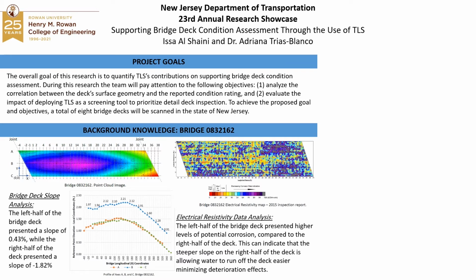By having a look at the results obtained from the 2 different assessment methods, we can tell from the bridge deck slope analysis, by looking at the gradient of the color for the left side of the bridge, that it has a flatter slope than the right side of the bridge. The results showed that the left side had a 0.43% slope, while the right half of the deck presented a slope of -1.82%. Taking a look at the electrical resistivity data analysis, it shows that the left side of the bridge presented higher levels of potential corrosion than the right side of the bridge.